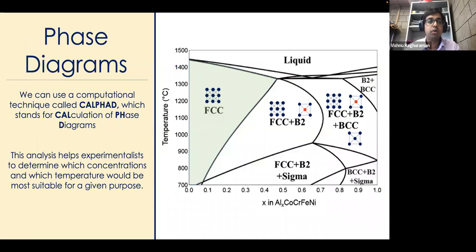And what all can you do using simulations? Well, firstly, going back to phase diagrams, you can calculate phase diagrams on a computer without having to, again, experimentally find out what phases are there, using a technique called CALPHAD, which is calculation of phase diagrams. So you would do a CALPHAD calculation and then inform experimentalists that certain concentrations would give you a single phase. And then that would be important information for experimentalists to then synthesize that alloy.